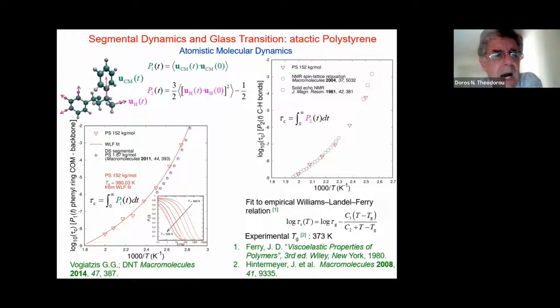One can also look at how the carbon-hydrogen bonds reorient as a result of thermal motion, both the aromatic and the aliphatic ones. And in a similar fashion, this time one can calculate a second Legendre polynomial reflecting the correlation of these bonds, the way in which they forget their original orientation, and accumulate again a correlation time as a function of inverse temperature, which now can be related to NMR measurements, because this is the type of motion that is probed by NMR. And the agreement is again very good. So if one uses a reasonable force field to describe the polymer and does atomistic molecular dynamics in the melt state, one has a good handle on these segmental motions that participate in the glass transition.